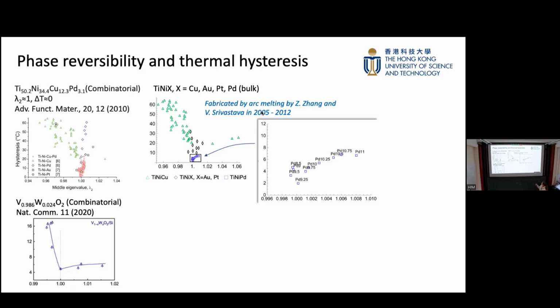So we have this kind of series, and we dope with different elements like copper and gold. This is different from that experiment. This is bulk, a bulk sample made by arc melting. So we really have this kind of body. Then we cut it, polish it, and measure the lattice parameter, and we find this material also shows the same result as the thin film materials.